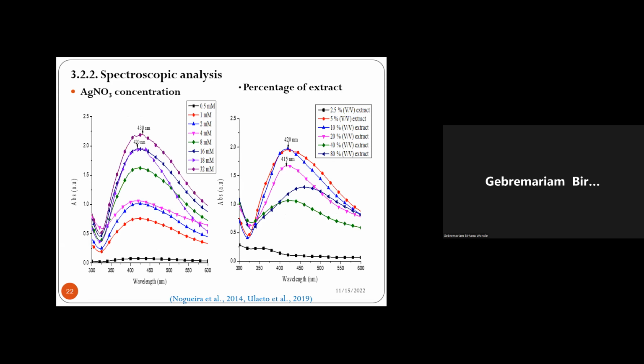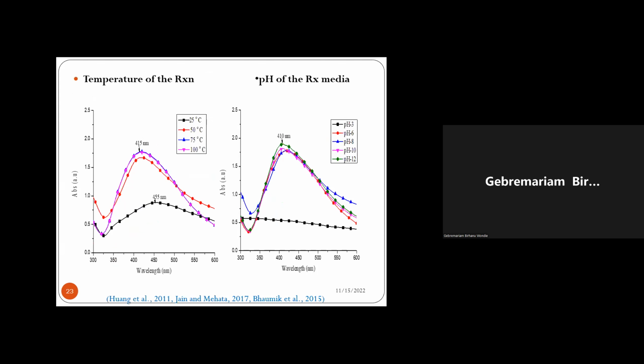The first graph shows the different concentrations of the silver salts that were used for the synthesis, and the second shows the percentage or amount of the plant extract that was used to synthesize the nanoparticles. So as you see from this graph, different concentrations were used, but the maximum yield was obtained after 16 millimolar of the silver salts, and after 10 and 5% of the plant extract.